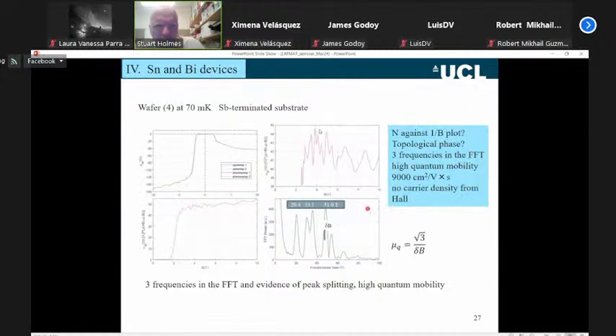I also looked at a second device. So this was a second wafer, and you can see on the bottom left here, this is actually Hall effect now. So Hall effect as a function of magnetic field, excuse me. And you can see here the oscillatory structure is much more complicated in this system. There are multiple frequencies. If you blow this data up, so this is an expanded scale now, you can see there are multiple frequencies going on. The only way to analyze this data is with a Fourier transform.